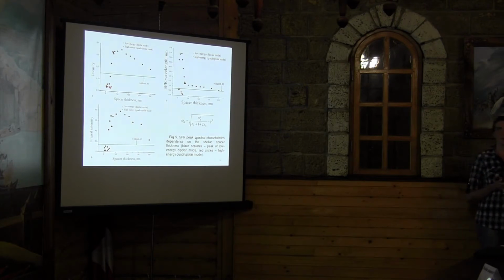And maybe we have an increase of extinction intensity because nanoparticles are like a second source of waves, and there is more absorption in that case. And there is a decrease of intensity here because of hybridization of states of dipolar and quadrupolar plasmons, and when we have smaller thickness and two peaks but not one, we have smaller intensity.